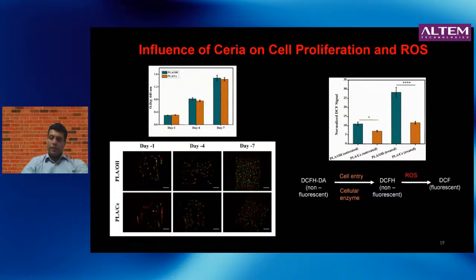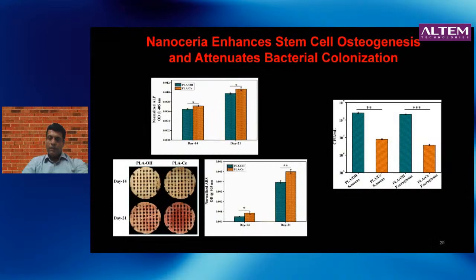Next, what we did was use these cells to look at osteogenesis, or bone formation. So here again, not surprisingly, you find that the cerium oxide helps in increased alkaline phosphatase and increased production of calcium phosphate, both at 14 and 21 days in culture. And you can see here that the one with Ceria has more red dye. It says there's more calcium phosphate than the one without cerium oxide. And that is because of the ability of these scaffolds to modulate ROS, which the one without the Ceria cannot do.